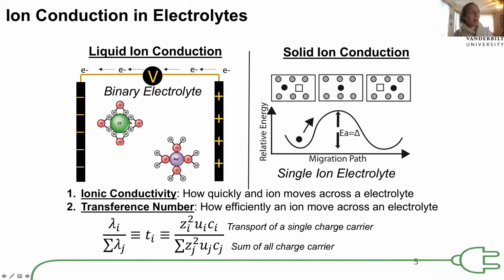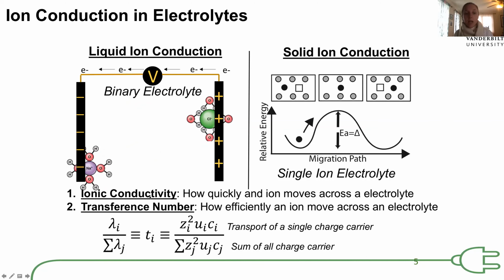So typically in an electrolyte, we take a salt and we dissolve it in a liquid solvent. That salt is what we call binary because you have the presence of both an anion and cation in your system. So when we're designing electrolytes, we typically look to two transport properties in particular. We think about ionic conductivity, which is how quickly an ion can move within a solid or solution. And we think about transference number, which is how efficiently an ion can move in a solid or a solution. And so in the case of a binary electrolyte where you have two charge carriers, this transference number is going to be less than one.